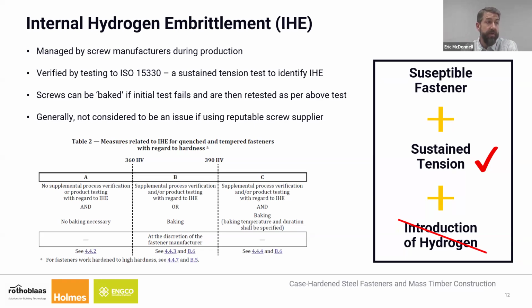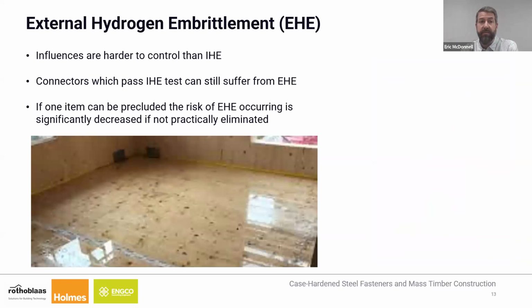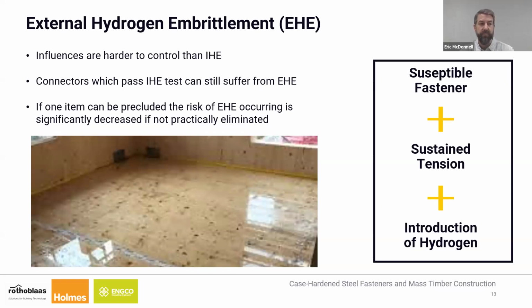But you may have shown that through the manufacturing process there's no introduced hydrogen, but now these screws have to go live out in a construction environment. There are important steps to be taken during the storage of the fasteners to make sure they aren't exposed to moisture. And then, per this image here, often our job surface is quite wet, so that we have free water. If that sits there for too long and exceeds what the coating can do, you're also going to start to get corrosion of that coating, which could then introduce hydrogen to the core.